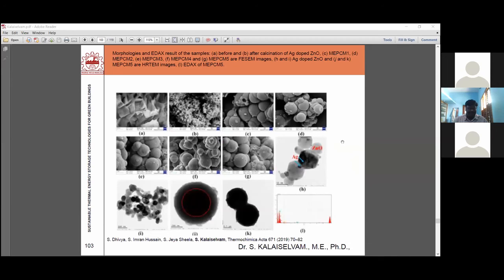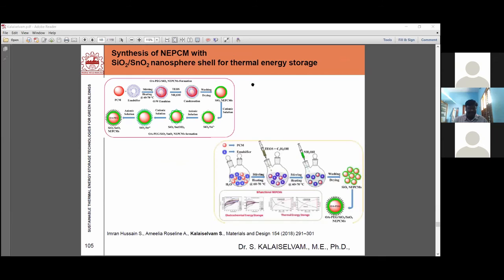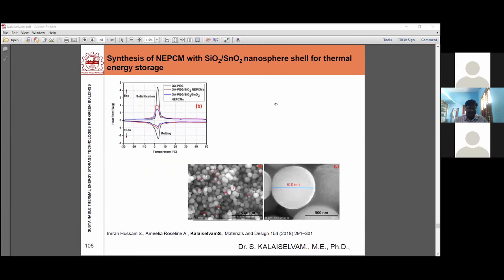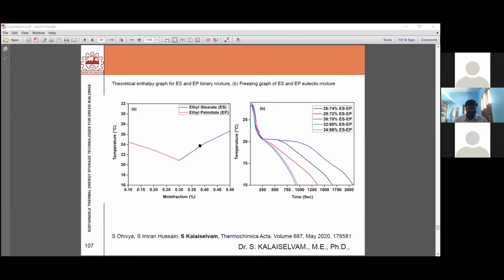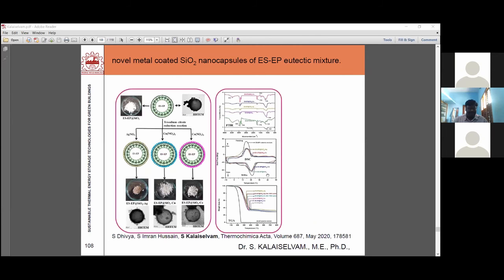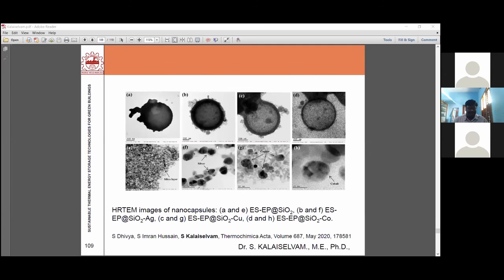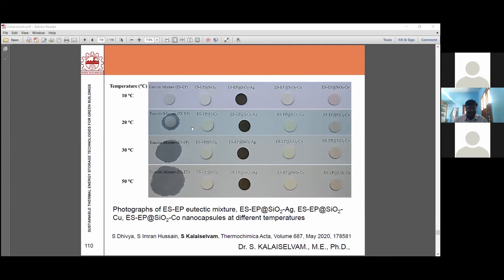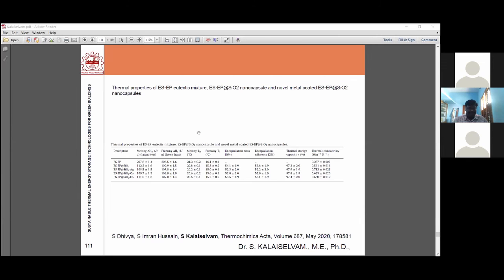And this is again micro-encapsulated PCMs with the Ag and zinc oxide dope. This is the micro-encapsulated PCM with cell PCMs with SiO2 and SnO2 material, PCM nanomaterials. It's again the curve, the mass fraction of the eutectic PCMs. It's again SiO2 nano-encapsulated PCMs. So it will be like that. You go for the studies. The same type of studies has to be done to confirm how it would be.